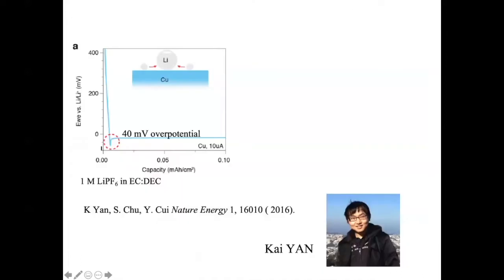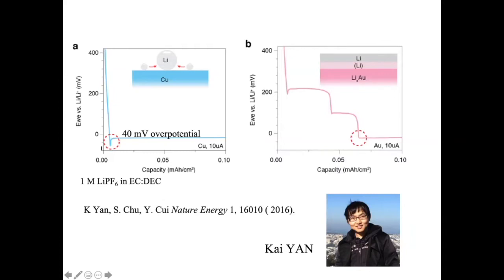So with this observation, let's go one step further. Let's look at this voltage curve, lithium deposition onto copper, shown on the left right here. This nucleation barrier is highlighted by this voltage dip of 40 millivolts at a very low current density, 10 microamp per centimeter square. But you can find other substrates such as gold. Here is a lithium plating highlighted right here. There's no voltage dip. So there is a clear difference between different materials. Kai Yan was my postdoc, now working at Apple, and discovered this and said, well, let's try to understand this. This is very important for us to control lithium metal deposition down the road.